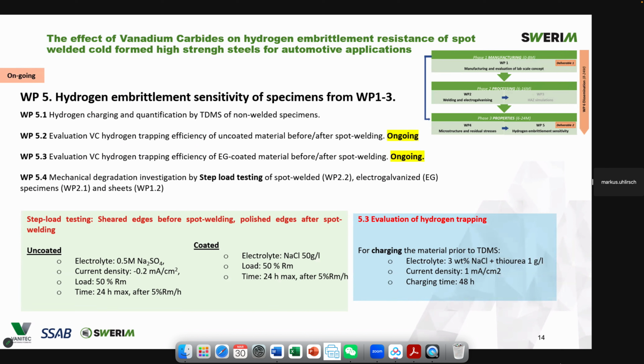Here we can see how the hydrogen embrittlement sensitivity was analyzed. We charged the samples according to the procedures in the colored boxes below. In the green box, we see the procedure for the samples for the step load test, which is some kind of constant load test. In the blue box on the right, we see the procedure for the samples for the TDMS analysis, which measures how many ppm of hydrogen are in the material.